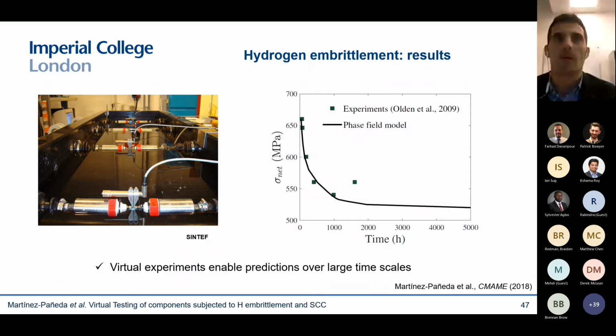These are a set of maybe more interesting experiments. These were done in Norway by the group at SINTEF. You can see they have a seawater bath, and they immersed some metallic samples, I think a duplex stainless steel, into this seawater bath. Then they subjected each of the samples to a constant load, but at different loads.